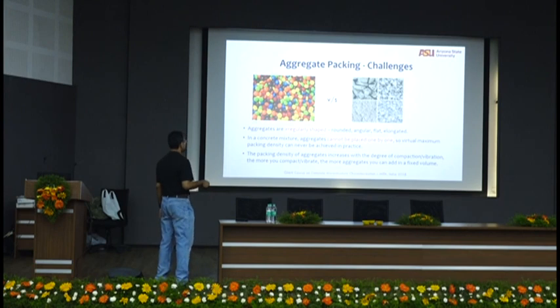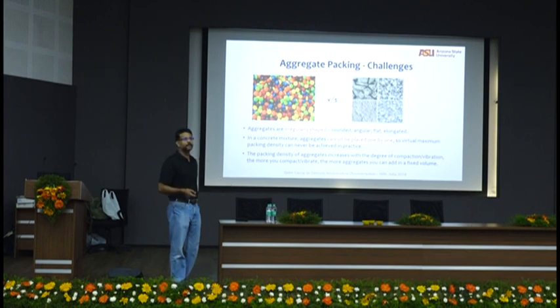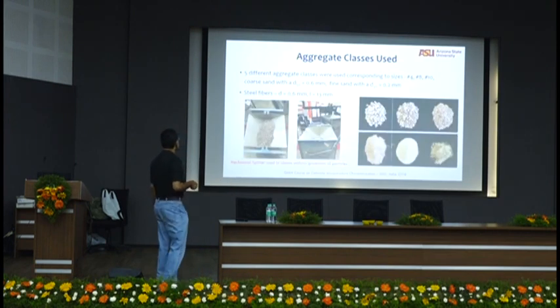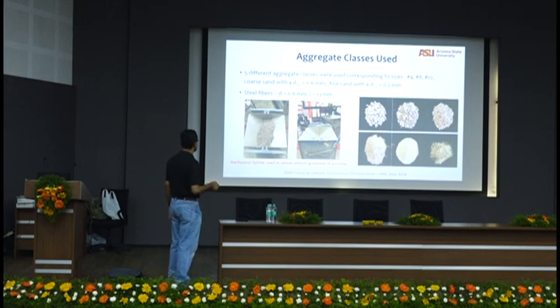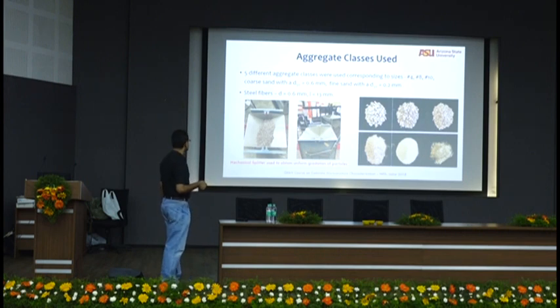So in a concrete mixture, aggregates cannot be placed one by one, so you have to get virtual maximum packing density. So you have to do it through compaction and vibration. That's why you compact, right? You compact and vibrate, because just by placing, you will not get maximum density. So we use 5 different classes of aggregates, and we use steel fibers 0.6 mm diameter and 13 mm long.